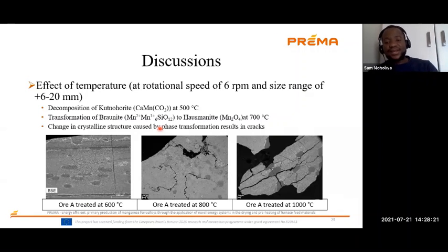Now we move to the discussion of the effect of temperature. As mentioned earlier, temperature increases the decrepitation index of this ore. Now the main question is why? Why does increasing temperature increase this DI? One of the reasons is due to the decomposition of kutnohorite, which has this ideal composition. This kutnohorite decomposes at 500 degrees Celsius.